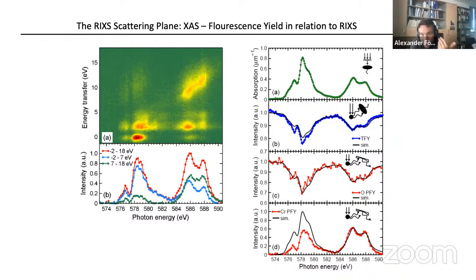And then we have to acknowledge that we have to be very, very careful when we want to assign and count stoichiometric ratios out of simple fluorescence measurements. That seems to be very dangerous for the simple reason that it's basically impossible to do a fluorescence detection which fulfills the Lambert-Beer condition, unless you have a thin film sample, which could be a thin liquid jet, which could be a monolayer in a sample.